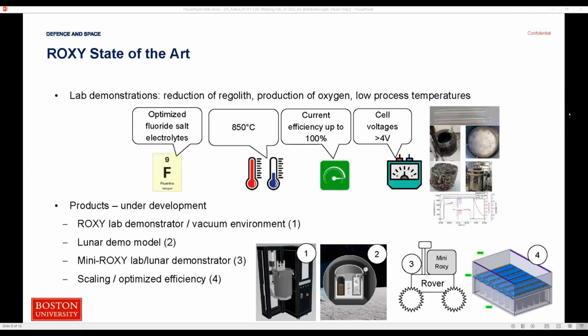Okay, so here's some information on where we are with Roxy. We have demonstrated the process in the lab. We have reduced regolith and produced high purity oxygen. We could reduce the process temperature to 850 degrees. We could show that we have a very high current efficiency and can operate at relatively high cell voltages.